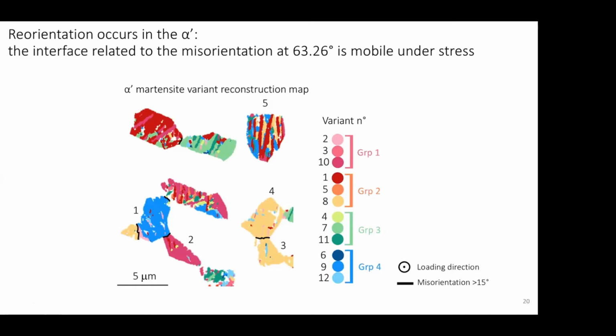So, based on the fact that the fraction of the misorientation at 63 degrees has greatly decreased under the effect of deformation, and that in some grains just 1 variant remains after deformation, we can see that the interfaces related to the misorientation at 63 degrees are in fact mobile under the effects of deformation. And when you have such a deformation mechanism, we talk about reorientation. It was quite surprising to find it, because it's usually a prerogative of shape memory alloy martensites and not the martensites in Ti64.